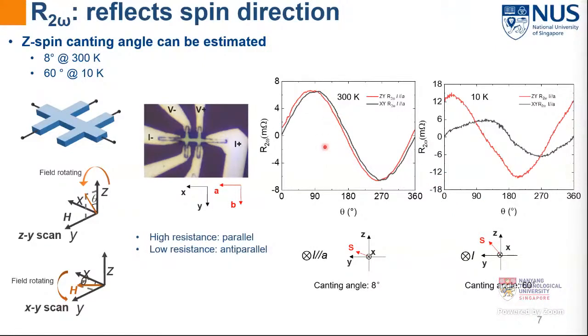By combining the XY scan curve and the ZY scan curve, the red curve and the black curve, we can see that the XY curve indicates that when the current flows along the plus X direction, the in-plane spin aligns along Y. For the ZY scan, its static deviation is from 90 degrees, which means that it has a small Z spin, which makes the canting angle around 8 degrees. However, when the temperature decreases to 10 Kelvin, the canting angle increases to 60 degrees.